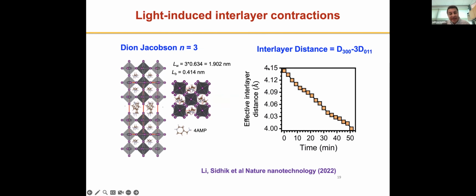And so we plotted the effective interlayer distance, and we got this by looking at the d300, which is this spacing here. This is the lattice distance for the out-of-plane 300. And then we subtracted from that 3 times the d011, which is this one here. So 3 times that gave us this interlayer distance, which is shown on the right here. And you can see that we go from about 4.15 angstroms to about 4 angstroms in this case.